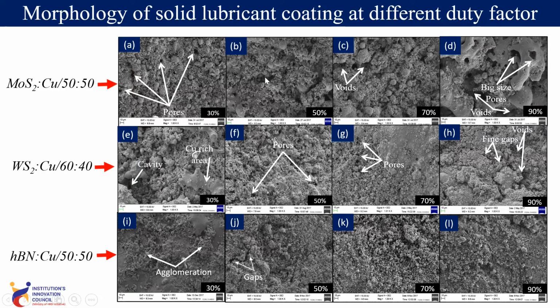So it is observed that at 50% duty factor, a good surface is obtained. Although when we are increasing the duty factor from 70% to 90%, mainly arcing is observed. So void formation, big pores and voids, some defects are observed. Similar results are obtained for WS2 copper coating, and for HBN copper coating at 70%, we obtained a good surface.